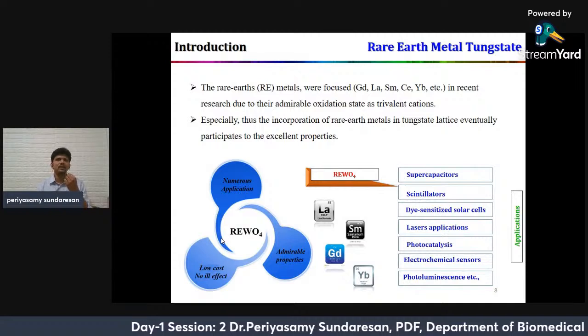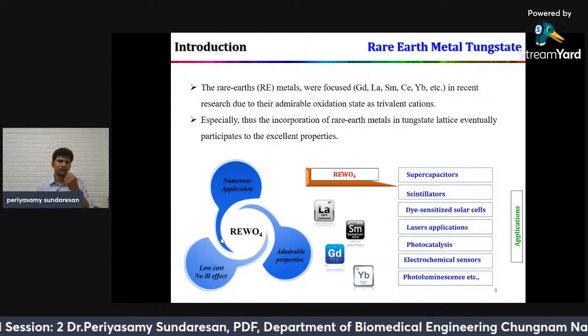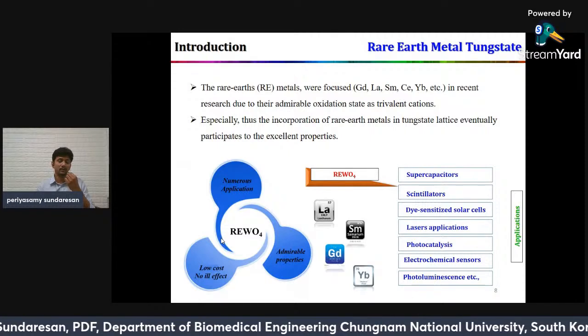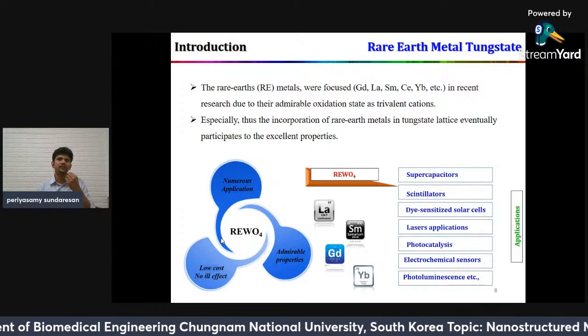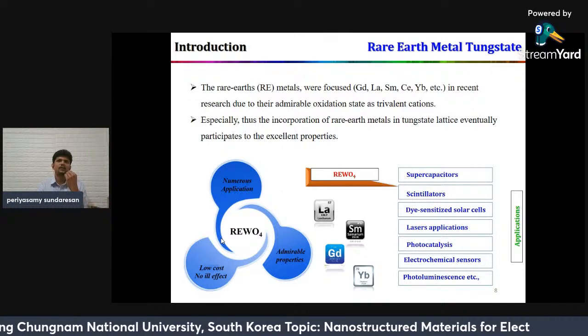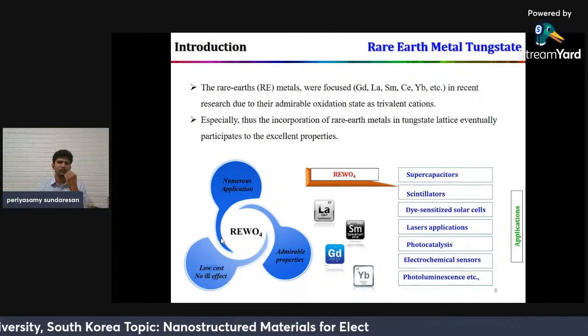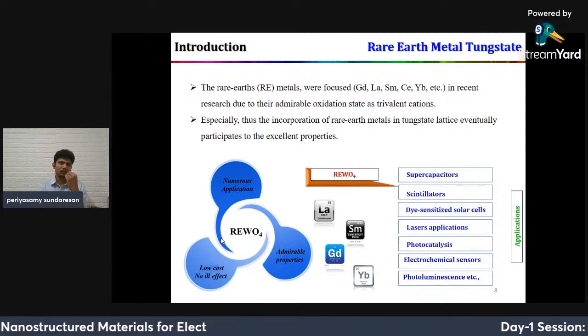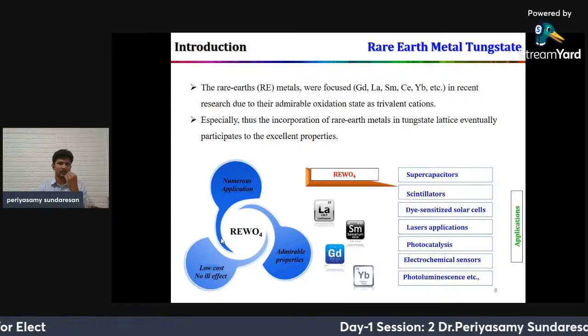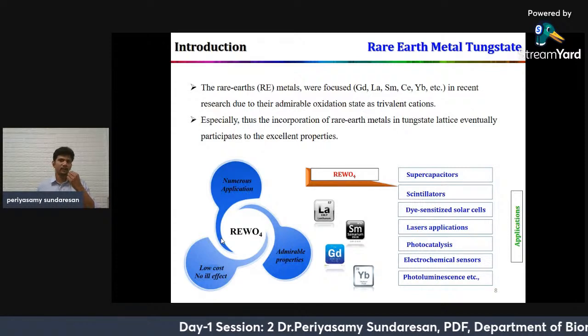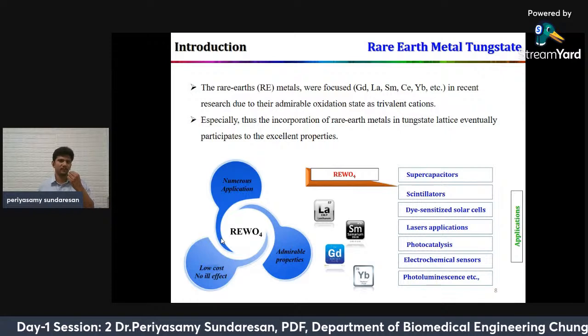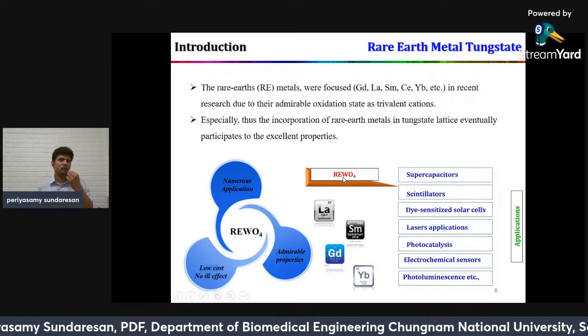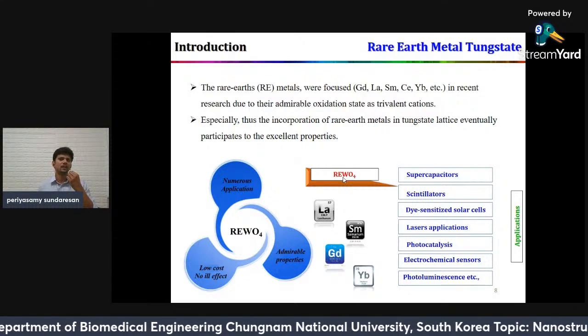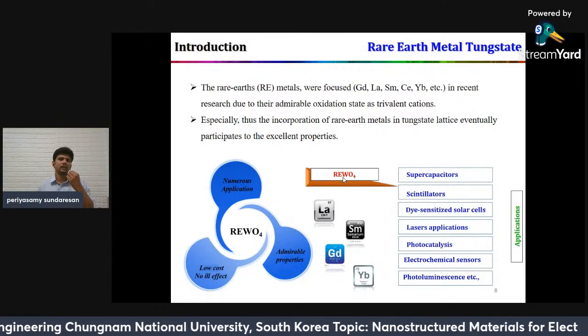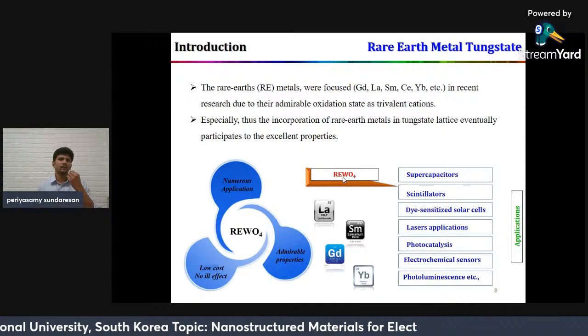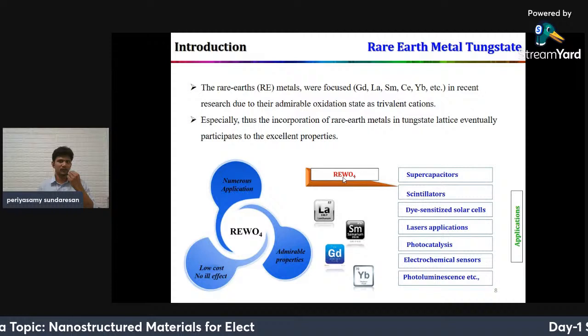Rare earth metal tungstate. We know very well that rare earth elements have higher oxidation vacancies compared to the S block and D block elements. The rare earth element group has more oxidation states. The common oxidation state is +3, but the S block elements are +2, and the D block elements are approximately +2 to +7. This is because the lanthanum group has the lanthanide contraction effect. This effect is very useful for getting more vacancies because the lanthanide contraction has a poor shielding effect.